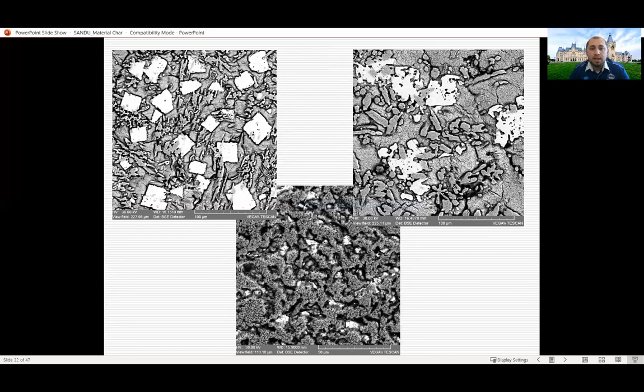Another example in here, some interesting samples. These are anti-friction alloys. As you can see here, the left upper corner is an anti-friction alloy. Also, the right corner is an anti-friction alloy. That means you can see the shiny, the brighter particles in there are the harder component, and the rest, which is grayish, is the softer component. So that means when those metal parts get in contact, they get in contact only on the shiny surface. That means a way of reducing the friction between them.